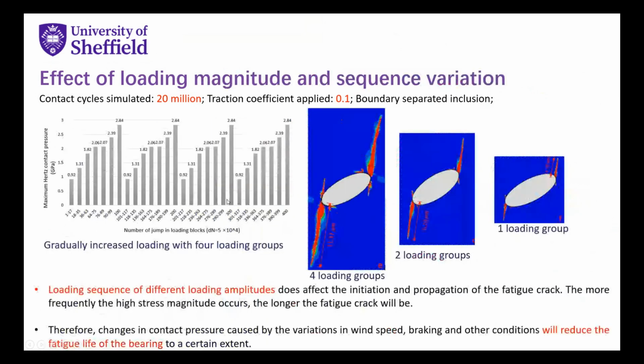Then if we change it 4 times, then I got 4 loading groups. So it changed 4 times from the smaller value to a big value, and when we compare these results together, we find that when it changed 4 times, with 4 loading groups, the crack length is longer than the 2 loading groups and the 1 loading group here. So the loading sequence of the different loading amplitudes does affect the initiation and propagation of the fatigue cracks. The more frequently the high stress magnitude occurs, the longer the fatigue crack will be.